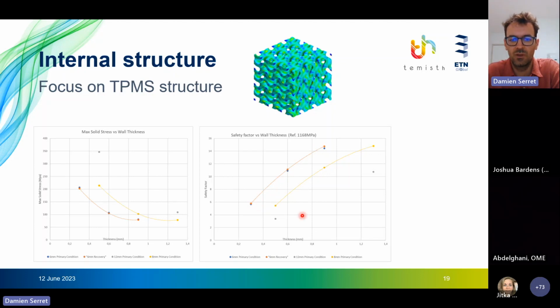And thanks to these results, you can see that we stay at a safety factor of 6 at the limit of the manufacturing process. For example, you can see this typical structure produced by an additive manufacturer, and the typical limiting thickness of this gyroid is around 300 to 400 micron. With this thickness, you can reach a safety margin of between 5 and 6.